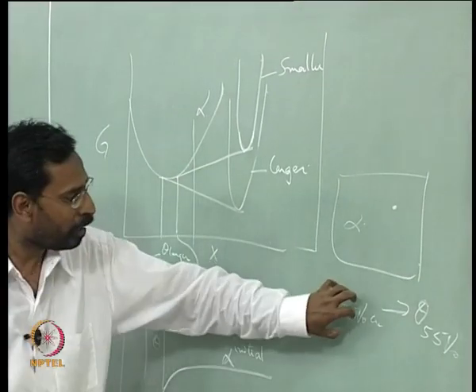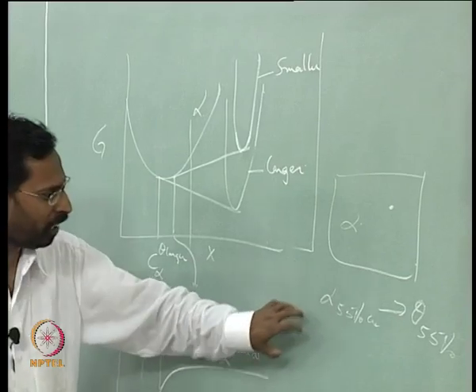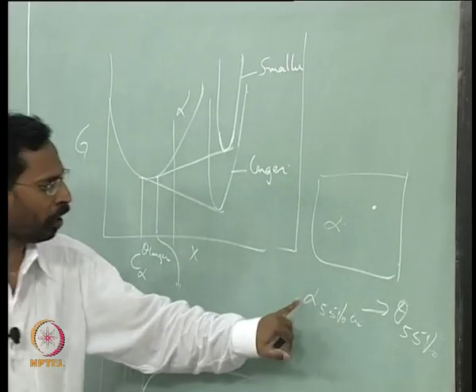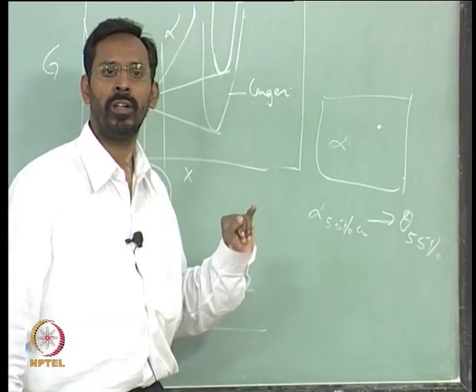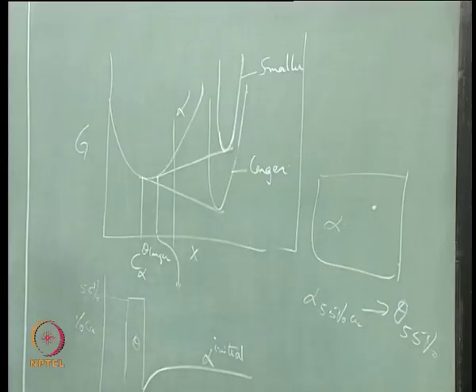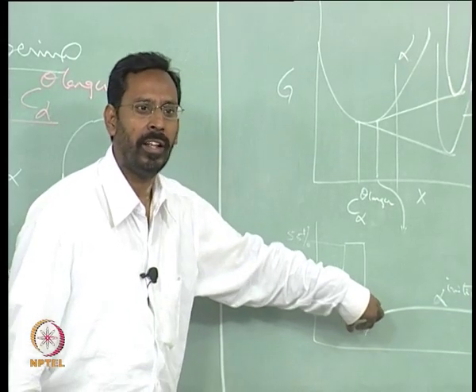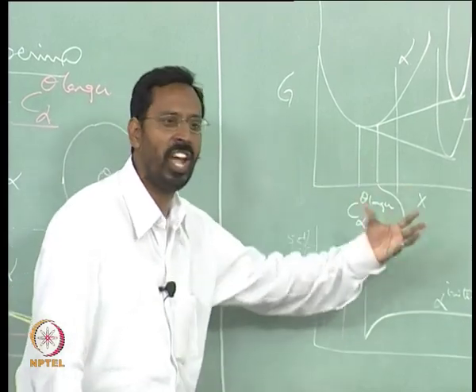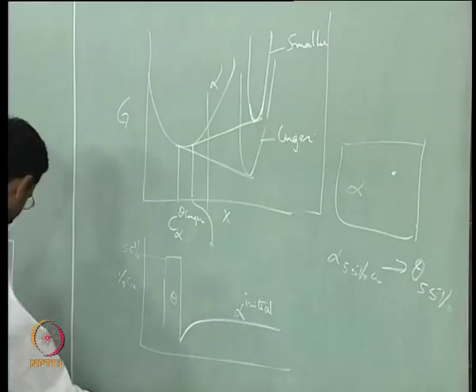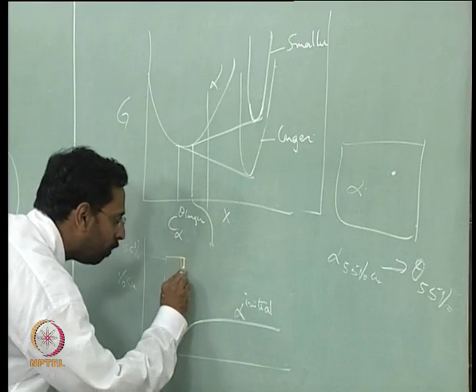So, once the copper atoms reach that concentration level, it is only a structural transformation now. An FCC structure changes to a theta structure. So, as the copper atoms get accumulated in that small region, that small region gets changed to the theta, and as a result now the theta grows by a small distance.